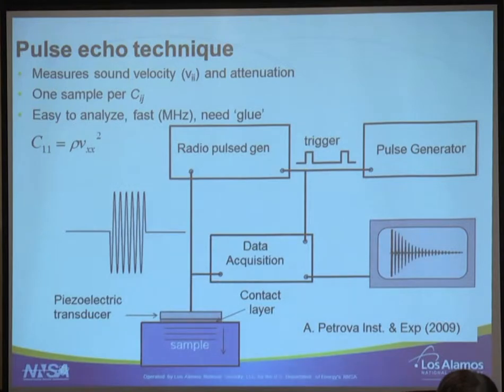This has a lot of good things and some drawbacks. The good thing is you can make this measurement really fast. If you're changing your magnetic field or changing your temperature rapidly, you can get a lot of data. The main problem is that getting a very good bond is complicated, particularly at different temperatures, because you have to make sure all the sound is transmitted back and forth. But the more cumbersome part is that you need a sample for each elastic constant you are measuring. So if you have a single crystal with low symmetry, you need several single crystals.